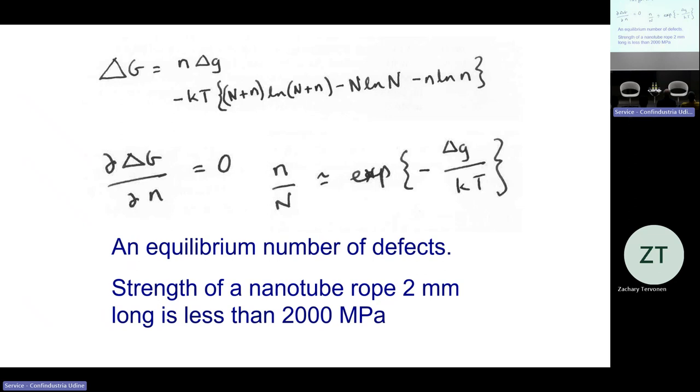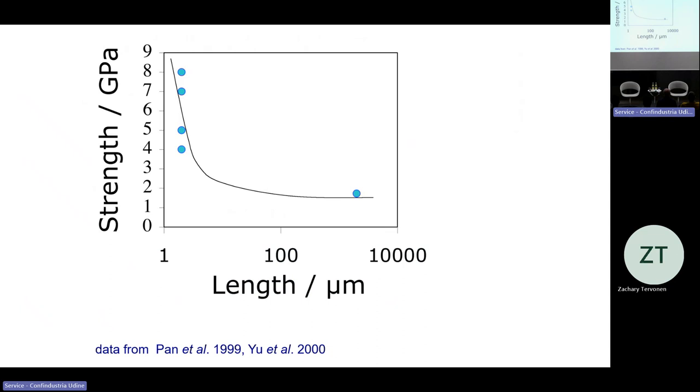So if you load that to 130 gigapascals, then the energy stored in there is 10 times more than dynamite. So if it breaks, you will have an explosion. That would not be a safe engineering material, because all the energy is reversible. It's just elastic. When we talk about toughness, we want the material to absorb energy. And plastic deformation, when the layers of atoms slide over each other, absorbs energy. So this is how the strength of graphene almost vanishes as you make it to a visible size.